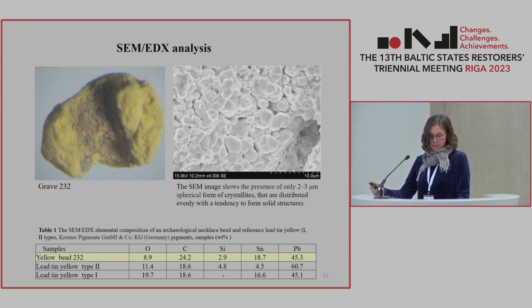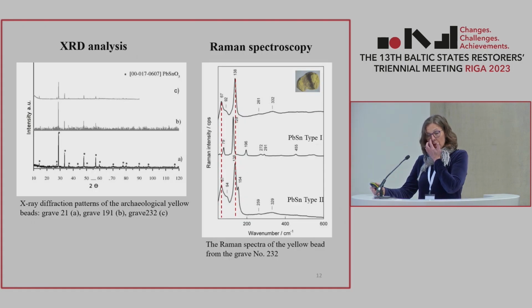The question arose whether it is possible that the glass beads were made on the basis of the lead tin yellow type 2 pigment. Diffractograms showed that all significant reflections of the bead samples were assigned to the lead tin silicon oxide phase having a cubic structure, which is described as the lead tin yellow type 2 pigment. All the bands visible in the yellow bead Raman spectrum coincide well with the comparative data of the lead tin yellow type 2 pigment.